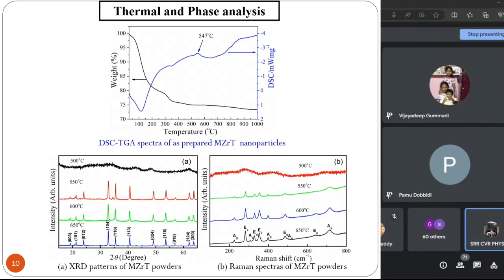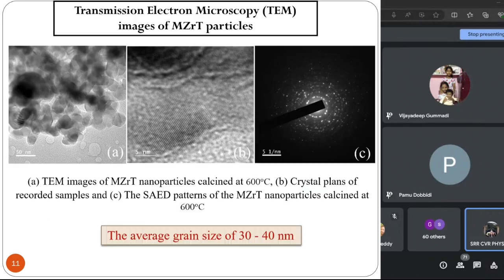So it is good with the XRD, but sometimes the problem with XRD is that you will not find if there are impurities present in the sample. That's where we have taken a Raman spectra, because Raman is a very sensitive tool to look at the impurities. We found that Raman also is not giving us any secondary phases. So to be on the safer side, we have chosen a calcination temperature around 600 degrees C. Can you go to the next slide, please?